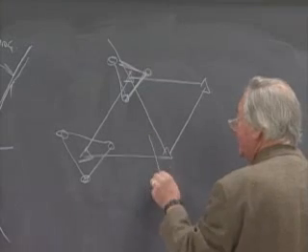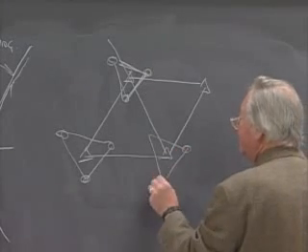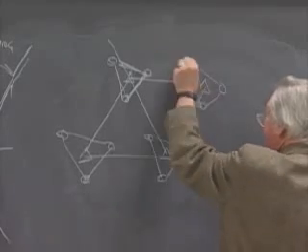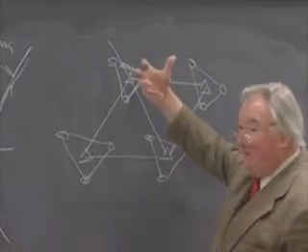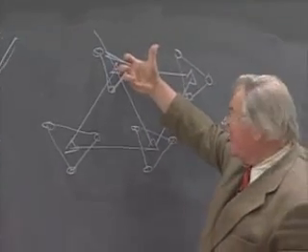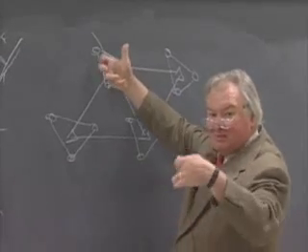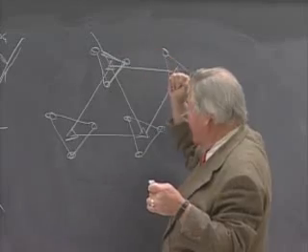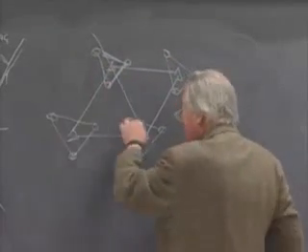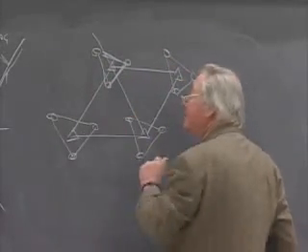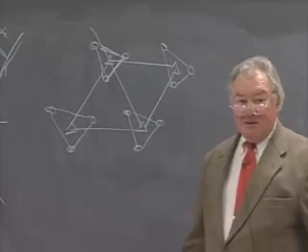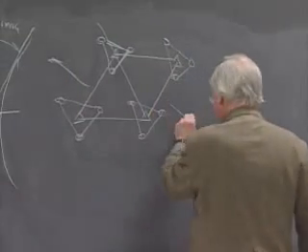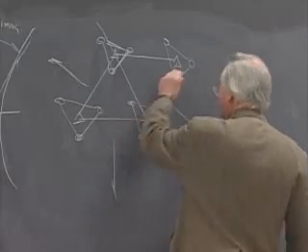So this is a material in which the bonding is very, very anisotropic. The bonding within these covalently bonded spirals, which are like springs that you might put on your screen door in the summertime, is very strong. Between these individual molecular chains, the bonding is very weak. So what happens when you heat this stuff up? It expands like the dickens in the direction of these weak bonds.